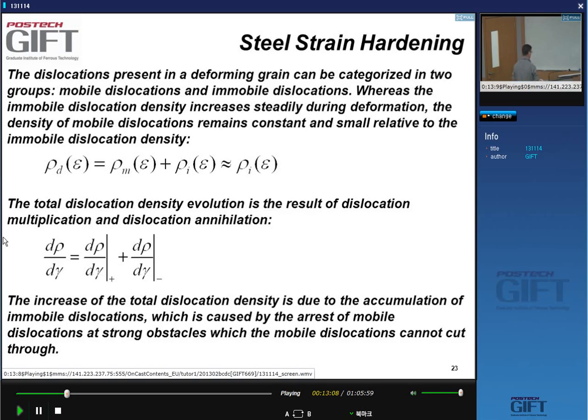The second point is, how do we compute this dislocation density? Well, it's simple. We say these sources here, these Frank-Read sources that come from double cross-slip processes, they generate dislocations. By stress, many dislocations are generated. So I have a process of dislocation generation. Then these dislocations run into each other, and they will form somehow, we don't need to go into details, forest dislocations. They're just stuck there. So there is a transition from mobile dislocations to immobile dislocations. Actually, it's the sources that produce the immobile dislocations.